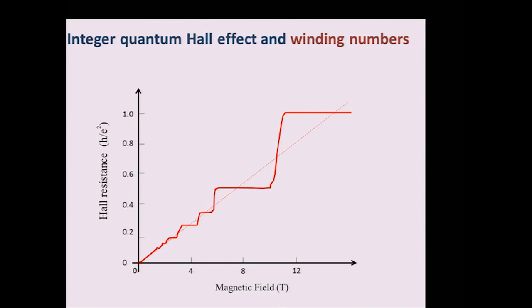In fact, this discreteness is closely related to what I mentioned before. One can find some regularity in this discreteness, and the steps are not arbitrary. If I call this my first step, it turns out the next one is half of the first step height, the third one is 1/3, and the fourth, 1/4. You can see that this has regularities, integer numbers associated with each plateau that appears in the data.